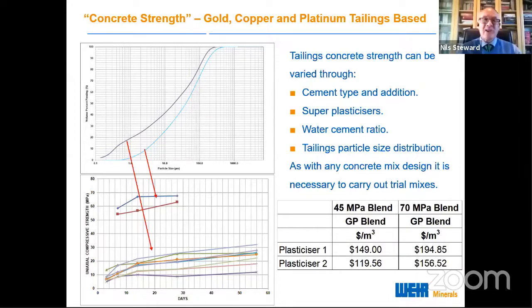The lower we get the water cement ratio, typically the higher the strength. Tailings particle size distribution is very important. In many instances, we need to actually blend the cements and the hydraulic and latently hydraulic binders, so that we can get the best packing that we can get to give us that strength. And as with any cement technology, the trial mix designs to prove the product are the way to go.